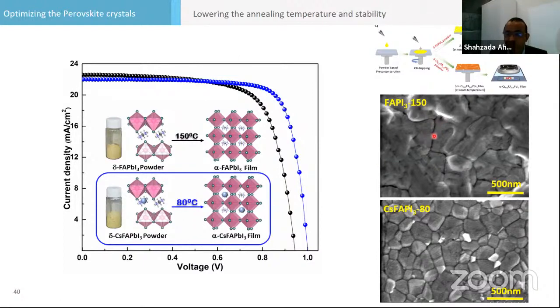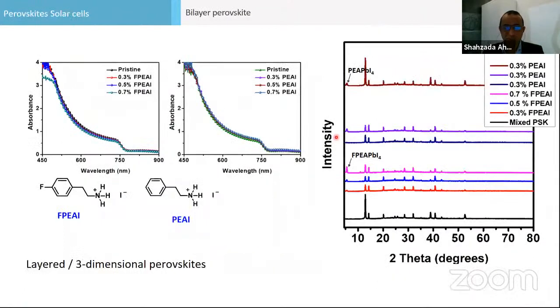And pure FA is not a stable powder. You can see that the crystals are not very well oriented. They are featureless, but if you put them with cesium and you heat them at 80 degrees centigrade, the pre-synthesized powder is very easy to fabricate now. Anybody can do that. It can be made on a kilogram scale. So you have a large size of crystal. And here we did spin coating. Let's go to the next one.